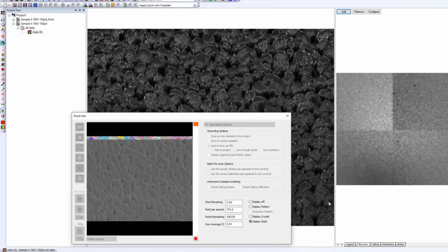And now you can see that even as we have significant topography, in most of those larger matrix grains, we are actually getting usable, consistent indexing. So what you need to do on a sample like this is collect your data at the low dose conditions. Sometimes you just have to accept that the patterns are extremely weak. And then afterwards, in many cases, you can actually do this NPAR process. You can optimize the contrast and image quality of the diffraction pattern and index it afterwards.